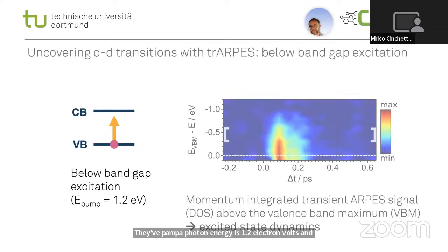experiments. So we have performed two sets of experiments, one with excitation below the band gap, so basically exciting only the first DD transition, and one set of experiments with above band gap excitation, which will basically excite not only the first, but also the second DD transition. The pump photon energy is 1.2 electron volt and 2.4 electron volt, respectively.